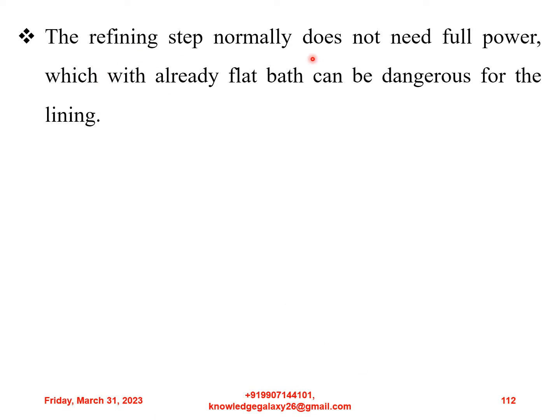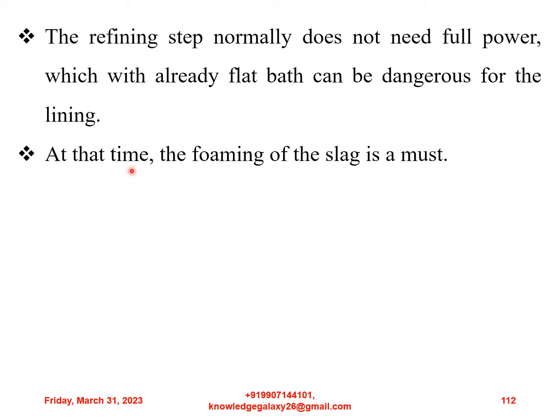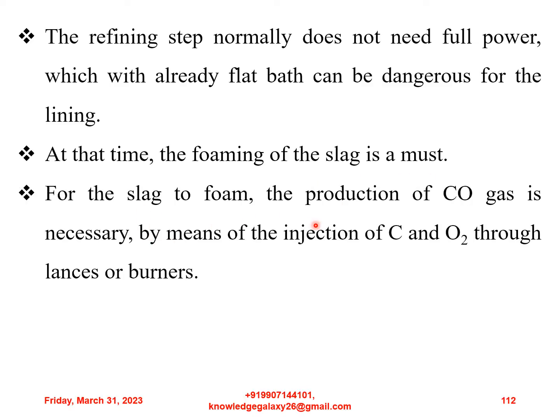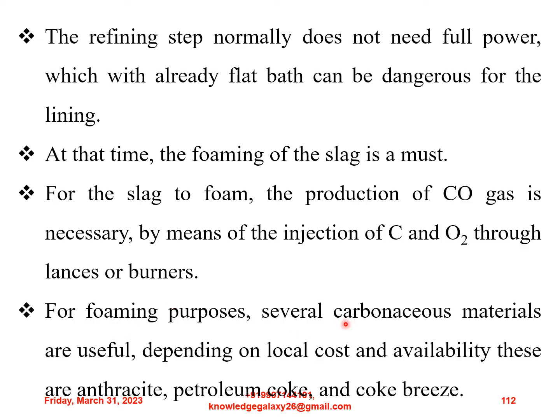The refining step normally does not need full power, which with an already flat bath can be dangerous for the lining. At that time, the foaming of the slag is a must. For the slag to foam, the production of CO gas is necessary by means of injection of carbon and oxygen through lances or burners. For foaming purposes, several carbonaceous materials are useful depending on local cost and availability. These are anthracite, petroleum coke and coke breeze, which I have already mentioned earlier in the presentation. I hope you remember that.